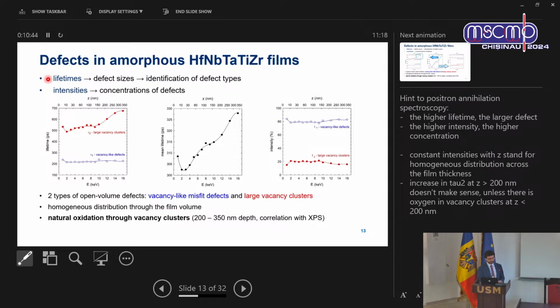So you can see we found 2 components of smaller defects, which it's difficult to call them vacancies when you have amorphous structure, but let's say they are something like vacancies and something like large vacancy clusters. And it makes no sense for thin films to have larger defects near the substrate than at the surface. This is not how thin film, metallic films grow.